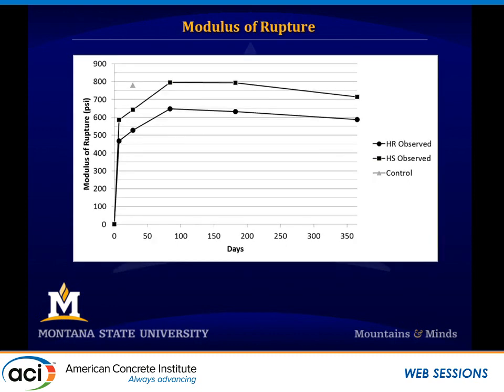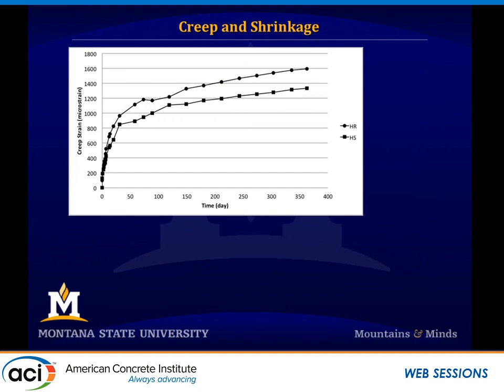Modulus of rupture, so the tensile strength of the concrete. You can see an effect there, which goes along. It's tied to the compression strength. So we had a decrease in compression strength, and you would expect that your tensile strength would be decreased. But it does meet the specification of 500 PSI that MDT wants, and we easily met that 500 PSI, even in the high wrap mix.